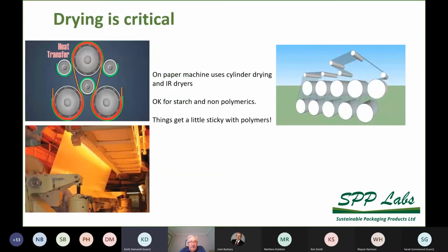And this restriction is really linked to drying. On a paper machine, the drying is usually by contact against heated cylinders. Some paper machines may have some infrared dryers after the size press or the film press, but mainly the drying is done with the paper in contact with heated cylinders. As a consequence, when you want to use more polymeric style barrier materials to achieve higher barrier performance levels, you run the risk of those materials sticking to the cylinders. Though some paper machines have invested in special coating and drying systems, one example is Kotka Mills in Finland, most do not have that. What that means is this essentially restricts most on paper machine solutions today to just being those fluorocarbon and wax replacement solutions. Anything else, you have to look to be doing things off the paper machine.